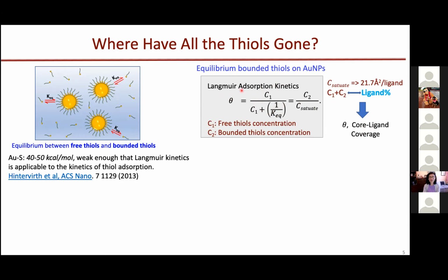This theta is also related to the bonded thiol concentration. So with the total of C1 and C2, you can relate it to the total thiol concentration we measured—the core ligand coverage.